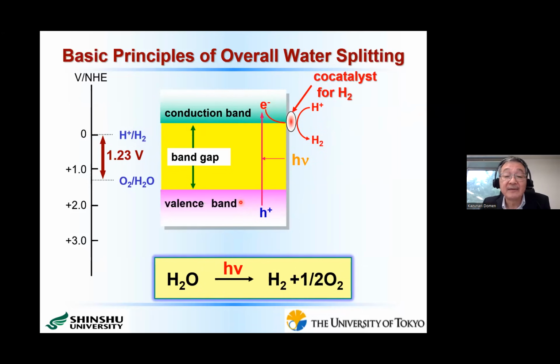On the other hand, if the valence band maximum is located more positive than the O2 evolution potential, then these photoexcited holes are thermodynamically able to oxidize water molecules into O2 molecules. But in many cases, especially in oxide type semiconducting photocatalysts, the surface of the photocatalyst itself works as the O2 evolution site. So here I don't show any co-catalyst for O2 evolution.